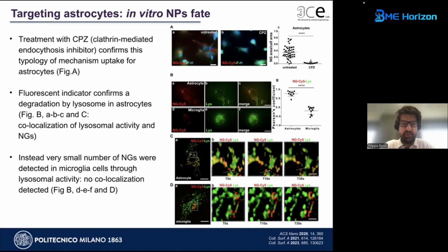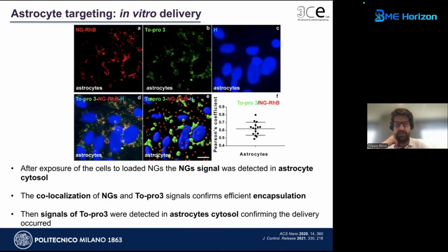fluorescent indicator confirm the degradation by lysosomes again, and the colocalization of activity confirm the degradation. Then what you can see from this analysis performed is that the amount of nanogel detected in microglia is low, and you cannot see colocalization with the microglia. We understand that this system can preferentially enter within astrocyte respect to microglia.